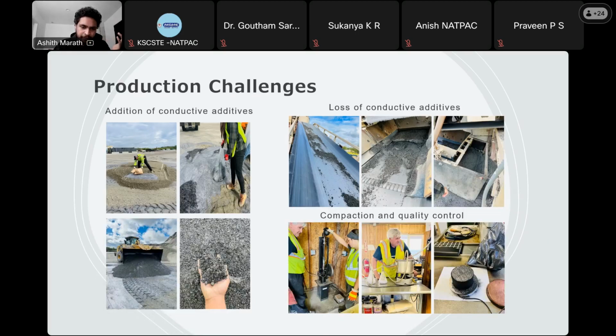So as I said in the initial slides, one of the main advantages of the APT is that you can also determine the production challenges, right? This was very insightful for us. On the left side image, you can see the mixing of the graphite and carbon fibers into the aggregates. I tried to mix it in the plant, and you can also see the blending of this carbon fiber and graphite. Everything was fine at this stage of production, and once we arrived at the mixing stage,